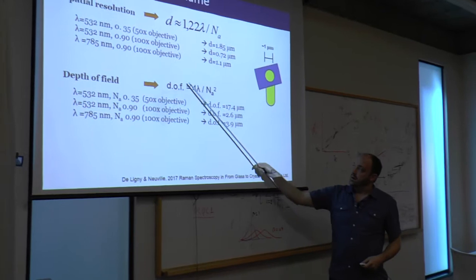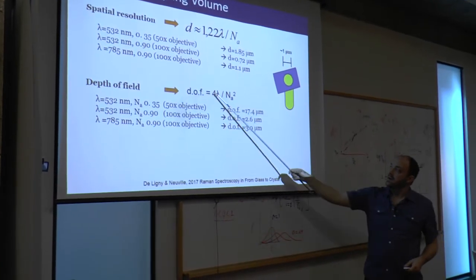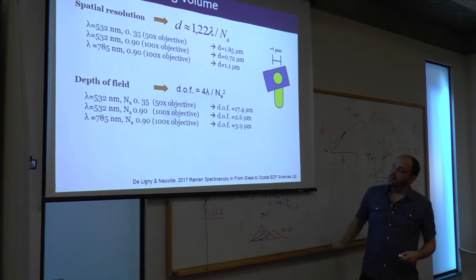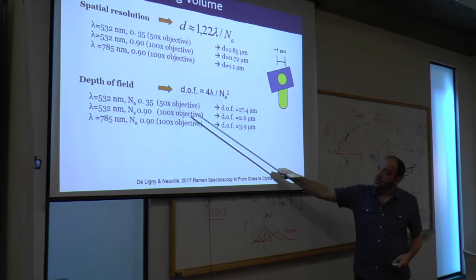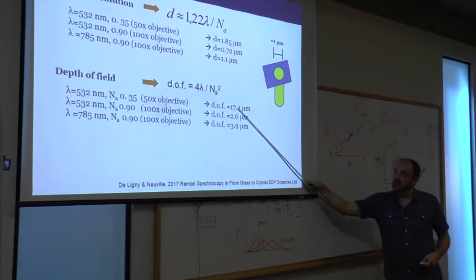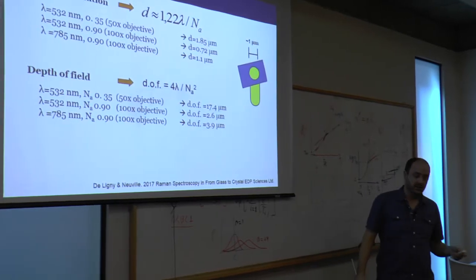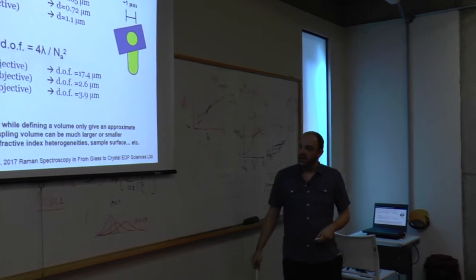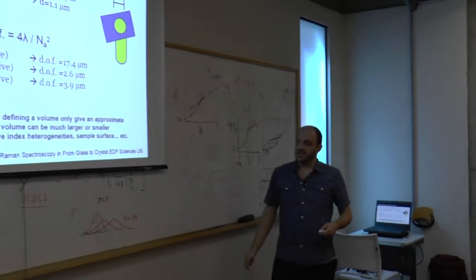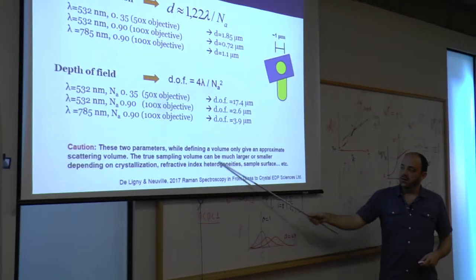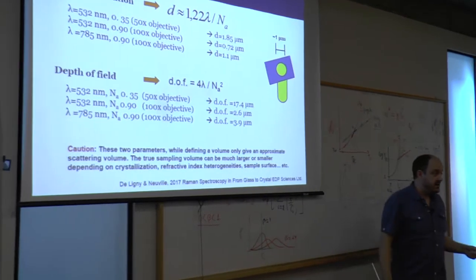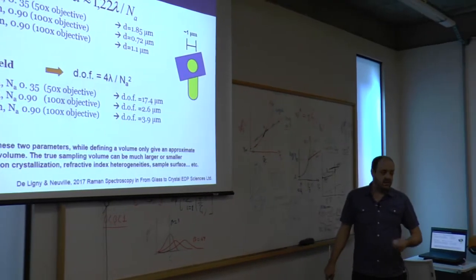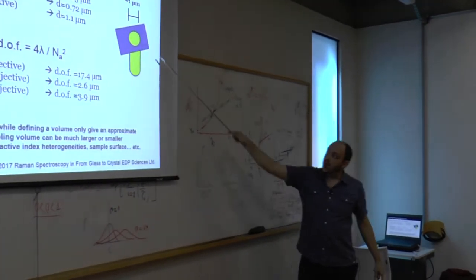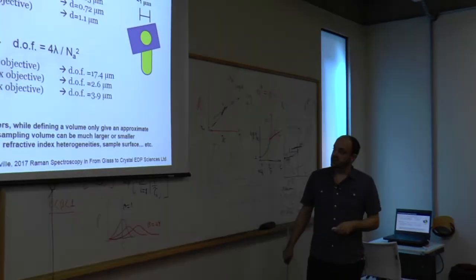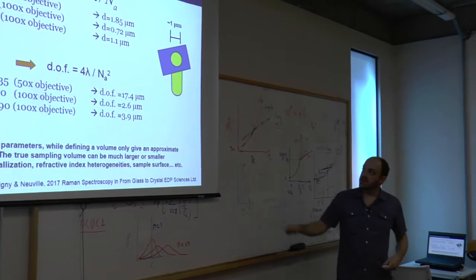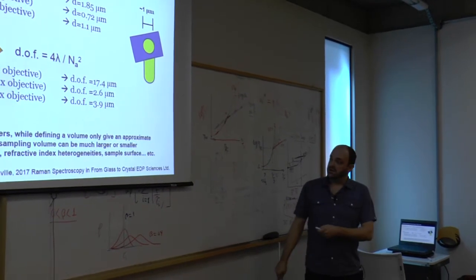The depth of field, how deep of the sample you're exciting, is equal to 4 times the wavelength divided by the numerical aperture squared. And so you can see again, with our green laser from 50 to 100, we go from about 18 microns down to about 3 microns of sampling depth. Again, this is a pretty crude estimate, and it really depends on what is happening in your sample. If you have crystallization that gets in the way, if you have other heterogeneities, it depends on the refractive index of the sample. If you have a lower refractive index, the laser can shine deeper, and photons from deeper and wider all around this area can get out and contribute to your spectra. But this gives you a nice first order guesstimate of the spatial resolution of this technique.